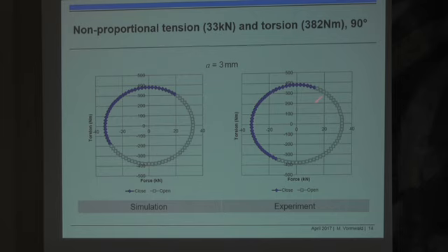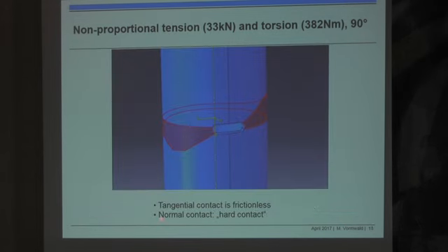And if we compare these two figures, we can say, okay, there is some similarity. Again, it's far away from being perfect. The point is that in our simulation, the crack is open for a longer portion of the cycle than is measured in the experiment. I might have forgotten that we did not take into account any friction so far. Maybe it's a problem of friction, but there are many other sources of errors when you do finite element-based node release schemes, plasticity, element size, and so on. So it's certainly a contribution, but not a lot.